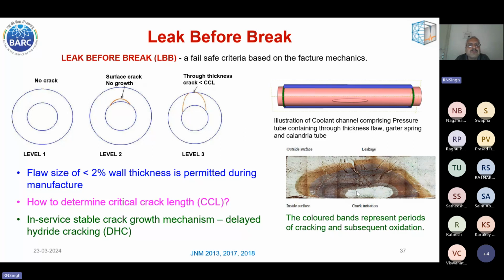So in the laboratory, this CCL and DHC velocity, all these things are determined by having a fracture toughness sample which is pre-cracked, and the way we do the fracture toughness test, we determine this CCL from both the material property as well as the operating conditions like hoop stress, wall thickness, and flow stress of the material. And then DHC velocity is determined again by carrying out the sustained load cracking test.